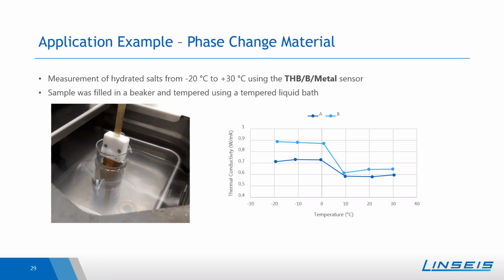As you can see in the picture on the left, the sample was filled into a beaker. It was liquid at room temperature, and the sensor was hung into the material so that more or less the complete sensor foil was covered. And then the setup was put into a tempered liquid bath to control the temperature of the sample.